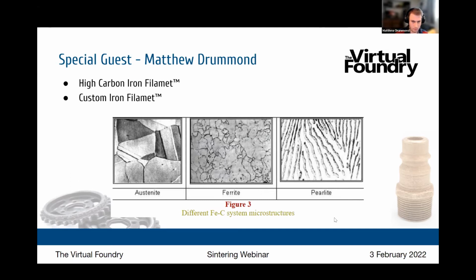I've tried previously, for the custom high carbon iron, a very slow cool down. I used the steel debinding process and got to the sintering temperature, left it for about 3 or 4 hours, and then I just turned the furnace off and came back in the morning. It was still fairly warm, and I just left it for pretty much the rest of the day, and it was nice and cool. And then last night I did more of a rapid cool down. Once it got to the sintering temperature, I turned it off, left it for about an hour, let everything settle a little bit, and then I opened it up, with about a half inch gap between the door, and let the air come out. And I got some very good results on my parts.